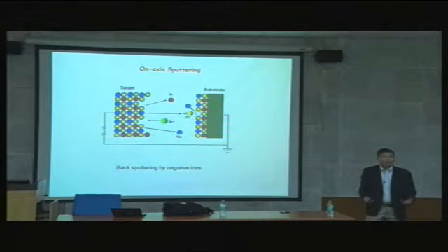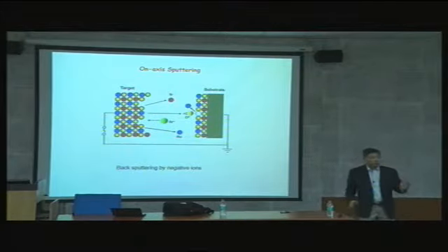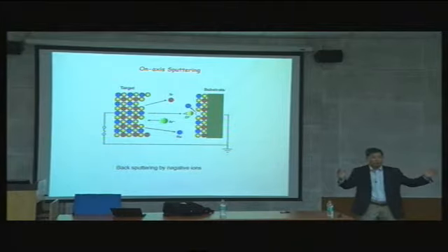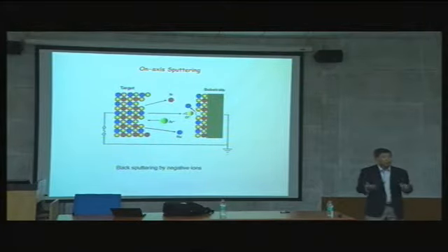So in order to overcome this problem, they make the distance very short. Usually in sputtering, a lot of chambers have a sputtering distance like this far, some this far. But they make it smaller and smaller, even a 5 centimeter distance. Very, very close. That's one way you overcome this problem. But you still have the negative ion issue, even though you have that high pressure.